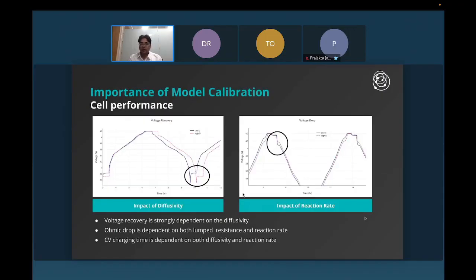Now, why it becomes important to accurately determine these parameters is also understanding the characteristics of the cells once they go through the charge discharge process, because that is very important to the evaluation of the cell performance. What kind of power availability we have for these cells, what is the charge and discharge time for the cells once you are discharging them at certain C rates. And there are certain important things that you would immediately observe: if you have diffusivity which is not being accounted for properly, you would clearly see that the CV time itself becomes much larger if the diffusivity is lower.